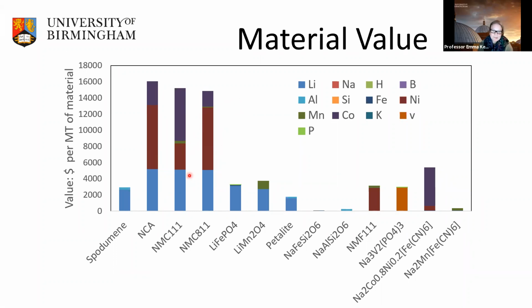I also decided to compare that to rock, spodumene. So in spodumene, you have round about 3 weight% of lithium. And interestingly, if you then look at the NCAs and the NMC, we have 7 to 8 weight% of lithium in these systems. So actually, these cathode materials are really quite lithium rich compared to even the rock that we extract some of this lithium out of. So the value prospect for these cathodes for recycling purposes is actually quite high.